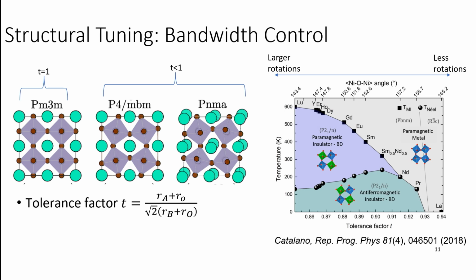And one consequence of that is that if you look at the phase diagram of the rare earth nickelates, where you have nickel here and a rare earth ion here, as you move along the rare earth ion in the periodic table, going from lanthanum to lutetium, you're effectively changing the effective radii of the ion that you're placing in these corners here.